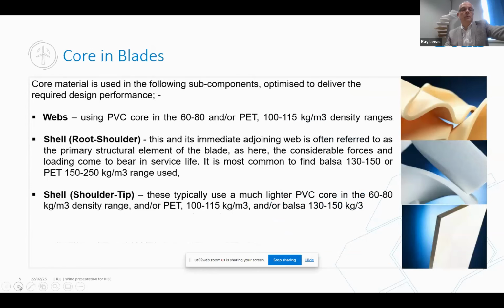If we look at the various areas in the blade, you can say there's simplistically 3 areas: the webs, and then the shells, and you can break the shells into the root and shoulder area and the shoulder to tip area. So in the webs, I think it was originally PVC materials, sort of 60 to 80 kilo, and then it has transferred to typically around 100, 115 kilo density PET materials. And of course, these make up the box section of the design.